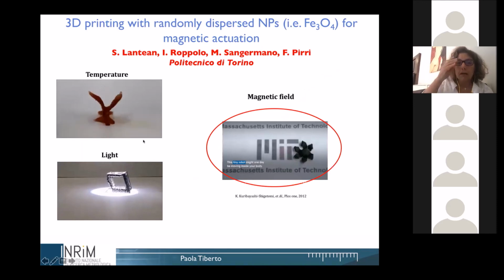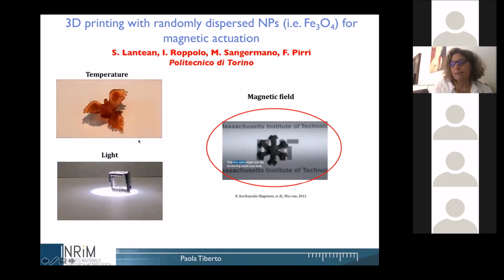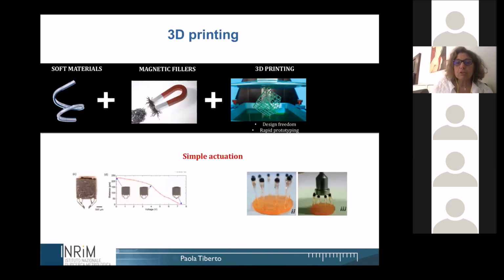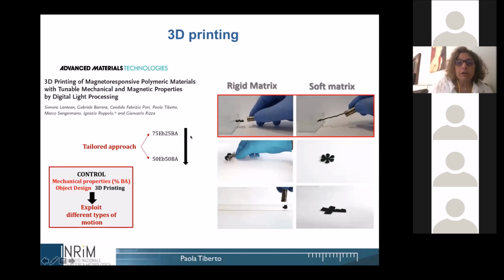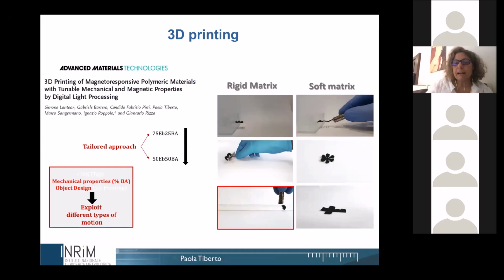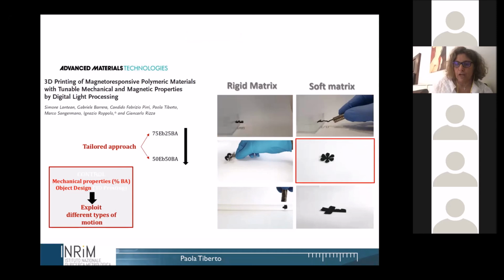Anyhow, I will briefly show you the idea behind using another very simple ferrite, which is magnetite, for magnetic actuation by simply dispersing the magnetic nanoparticles in polymers and then making a 3D printing in order to prototype some robots. This work has been done using two types of polymer. One gives rise to a rigid matrix in which the nanoparticles are dispersed, and here is the one with a soft matrix. You can see there are many different possibilities of playing with shape and so on.